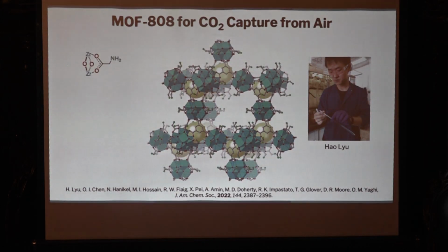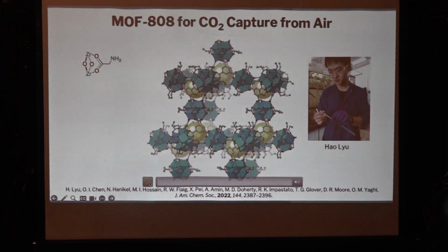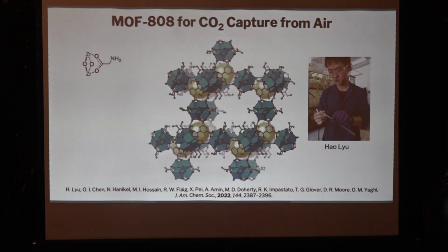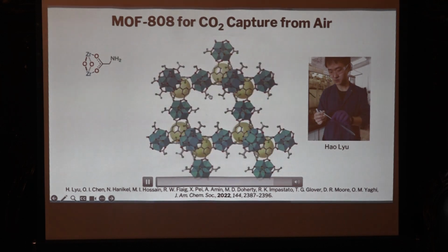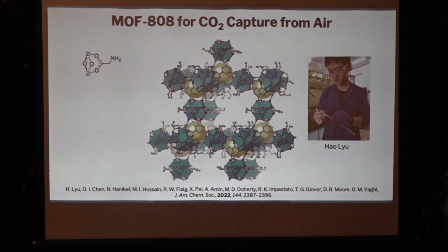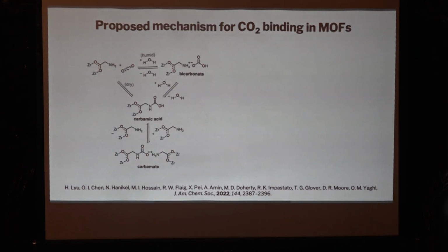Okay, so one of the MOFs, and I know that this is a MOF that's already being investigated here in the university by Alejandro's group. This MOF is amazing because it has sites within it, here within the pores, that could be functionalized with these amines. These amines are the green dots here. And so the structure is replete with these sites. It is these sites that are going to be plucking the CO2 out of the air. CO2 reacts with these amines, as you'll see shortly. In fact, on this slide, they react with CO2 to make, in the presence of water, bicarbonate, or in the absence of water, carbamate.